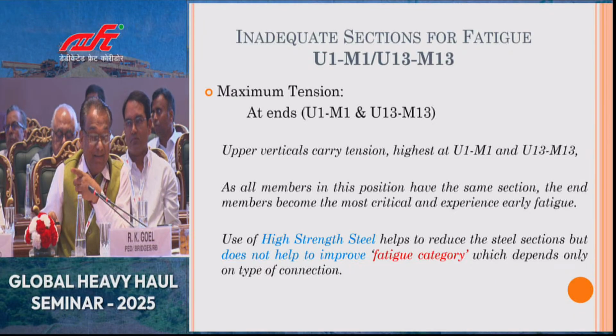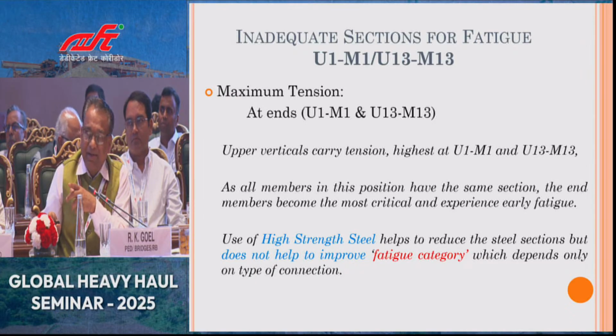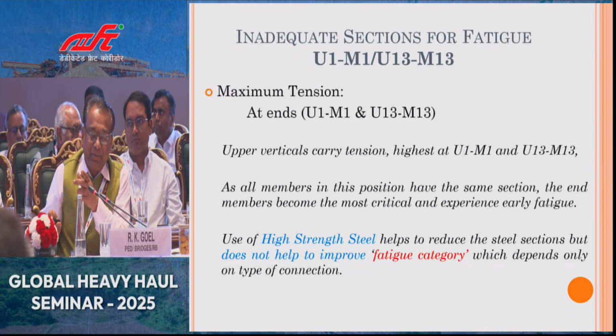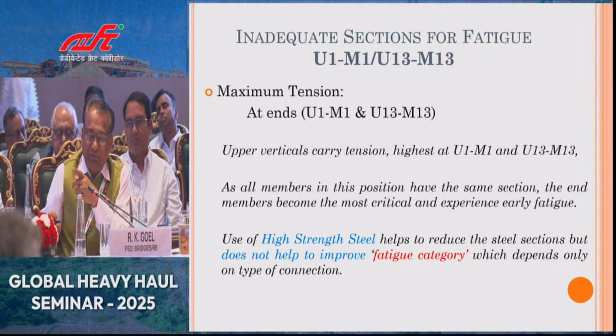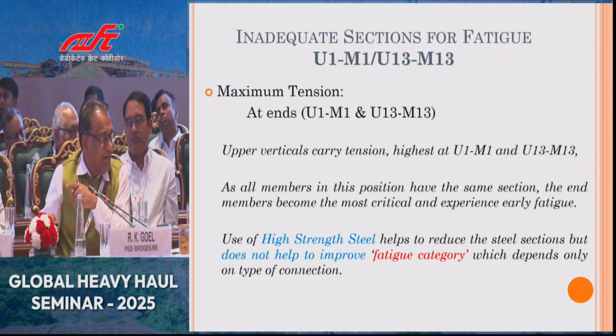And the high strength steel was used, which helped to reduce the section of this vertical member. But the fatigue category, which has been specified in the Euro codes, and from there we have borrowed it in our IRS codes also, doesn't depend upon the grade of the steel. So they have taken the higher permissible stress in the design, but it was not helpful, and that's why we have restricted the use of higher grade of steel by issuing a correction slip in our bridge rule, so that no more new bridges are built with higher strength steel and cause a subsequent failure at a later stage.